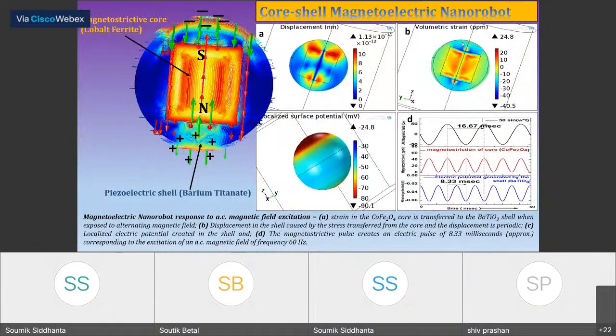Now, here is the structure from the simulations, where you can see a core-shell structure. The structure is a magnetostrictive cobalt ferrite core, which is coated with a barium titanate piezoelectric shell. When an AC magnetic field excitation is applied to this device, the core will expand and contract, and this exerts pressure on the shell. The shell, on the other hand, will generate electrical dipoles and a very localized high electric field. And as I said earlier, the generated electric field wave will follow the magnetic field excitation frequencies.